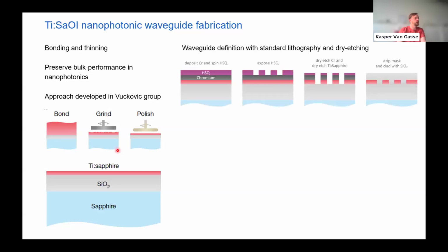And this also works great for titanium sapphire because it's a very hard crystal. It's not so easy to thin down. We figured out how to do it, but it's not trivial. And the nice thing about sapphire is that it also is very good for nanofabrication. People have been doing this for a long time, for example, to make micro lenses in the substrate of blue LEDs. And that is also something that is shown here.